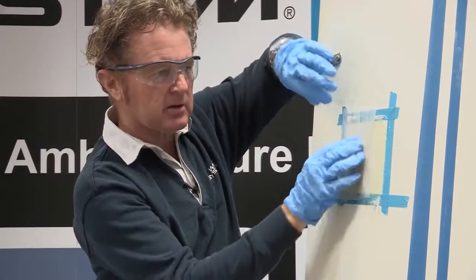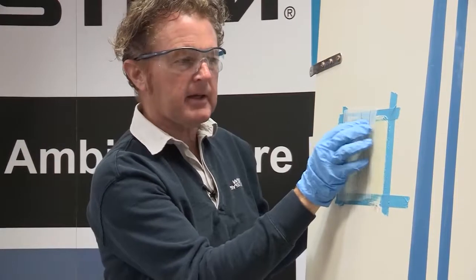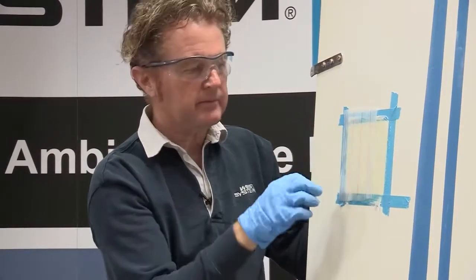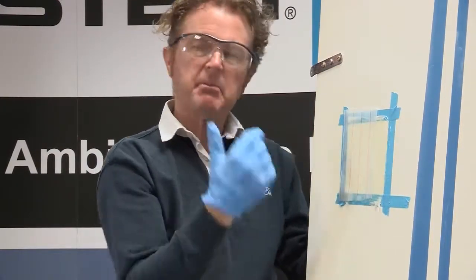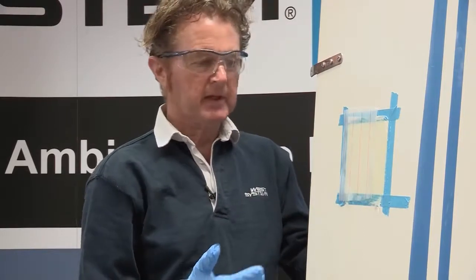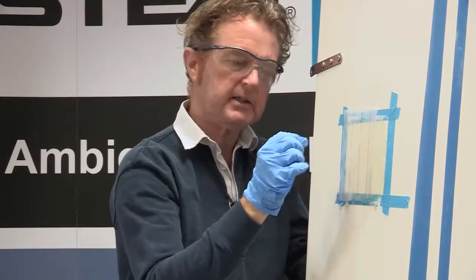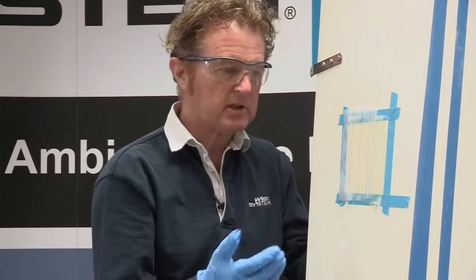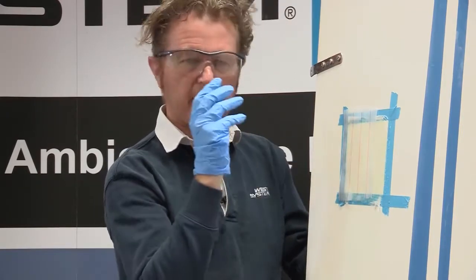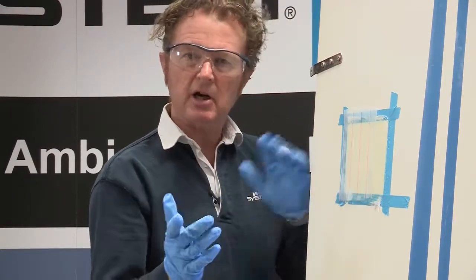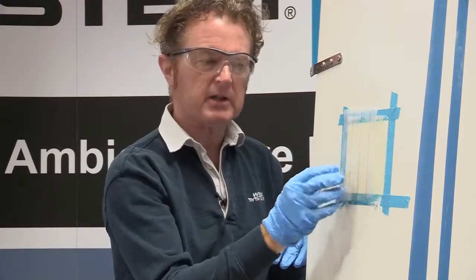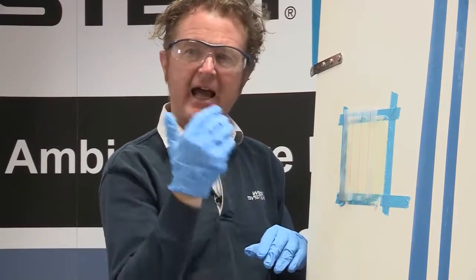leaving it to cure with the epoxy, once it's cured, you can rip it away. It's made from a nylon fabric. And once you rip it away, because it doesn't stick to the epoxy, it leaves a negative impression of the weave of this fabric in the surface. Now that's as good as sanding the surface.